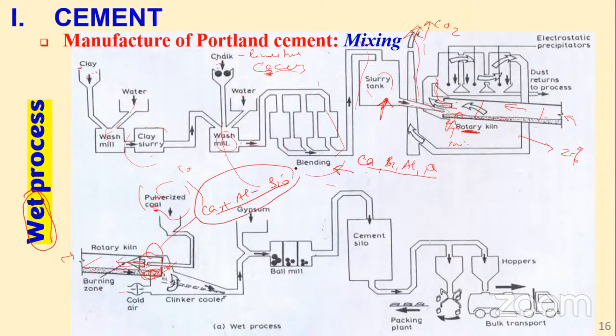This combines. And this is our sole purpose, why we are taking our material to this kiln, so that we end up having a different element. They are not separate now, but they have formed a compound. And what comes out here are those small balls I mentioned, the clinker, and they are taken to a cooler. Remember, the clinkers have sizes of between 3 to 25 millimeters. They are taken to a ball mill for crushing.